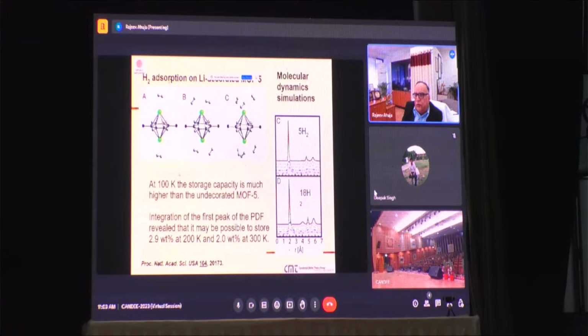So we have done the molecular dynamics simulation and plotted the distribution, and we can see the shape of the peak. I can have a desorption temperature increase from 77 to 200 Kelvin, and still maintain 2.9% of hydrogen in the system. And I can even have desorption at room temperature with 2% of hydrogen in the system. So here the weight percentage is not important, but the idea of the catalyst is working here also.